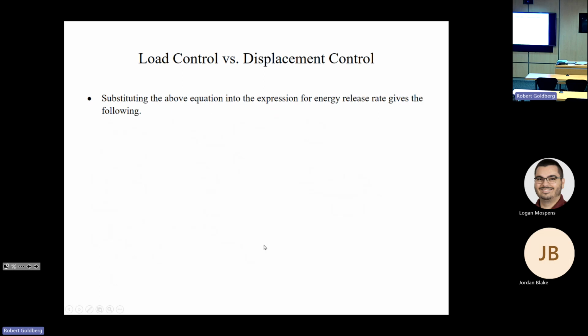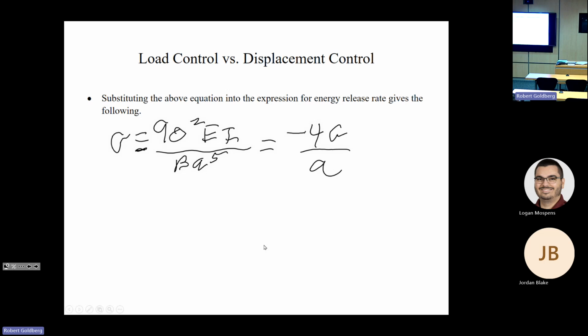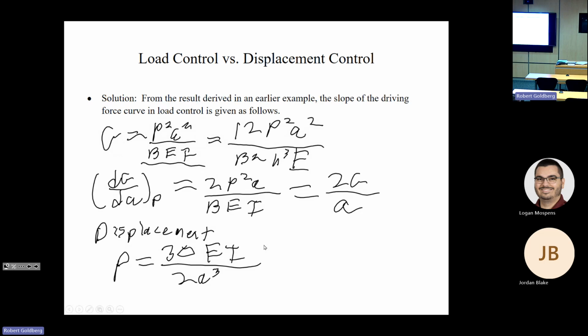So taking this expression into the expression for energy release rate, what we get is our energy release rate is equal to 9 times the displacement squared times the modulus times the moment of inertia, and this negative here, divided by b times a to the 5th. And if we simplify, it's -4 times the strain energy release rate divided by the crack length. What we did here is we know for displacement control what the P is, we stuck it in here, squared the P, canceled terms, and did some algebra.